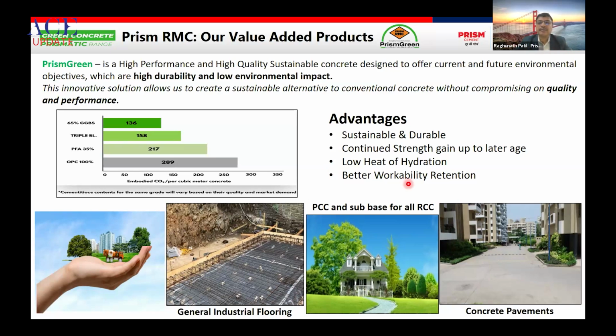So this is a sustainable and durable solution, because these particles, fly ash particles and GGBS particles, are very fine, finer than the cement, and they fill the voids inside the cement as well. Because of the secondary reaction, it makes the concrete very durable. It continues to gain strength for a longer age. In the case of mass concrete, when water exists in the concrete, it continues to gain strength, and it gets good strength in the structure.